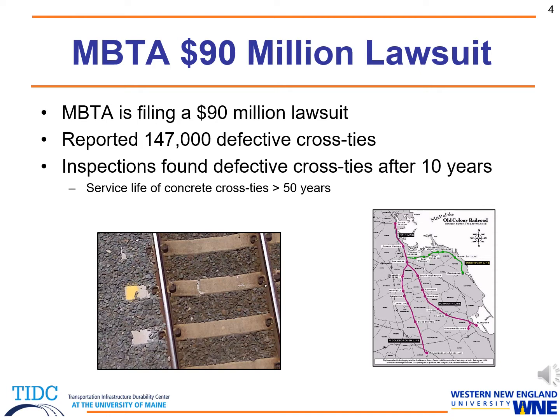And so for safety of the passengers, the MBTA had to require trains to decrease their speed from 70 down to 30 in these areas where cracked ties had been identified, and they even had to replace defective ones with wooden cross ties. And overall, there were a reported 147,000 defective cross ties.